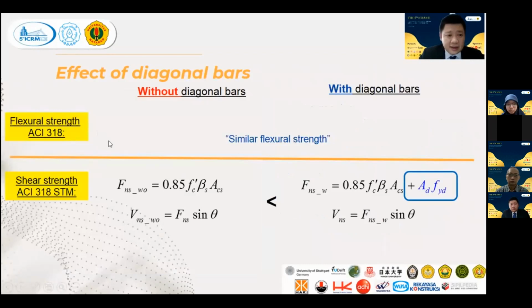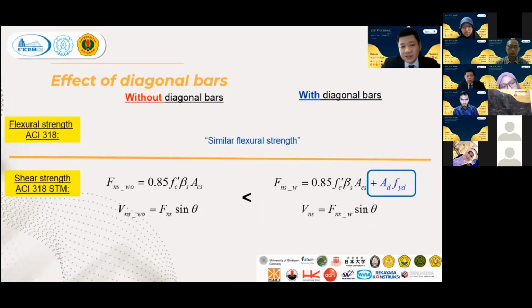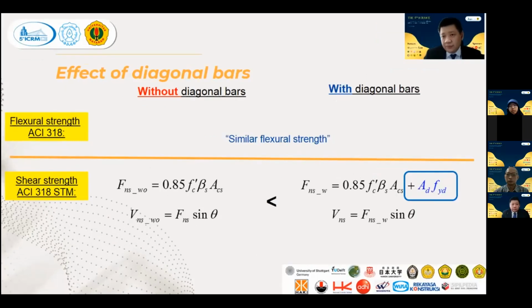The reason being like this. Under the similar flexural strength, for specimens without diagonal bars, we can only count on the concrete to resist the shear strength, as shown in this equation. However, if you have diagonal bars, then we can count on additional contribution from the diagonal bars. The vertical component from the diagonal bars is also very significant here. Therefore, you can have higher shear strength for specimens with diagonal bars. Therefore, you allow better development of its full flexural behavior.